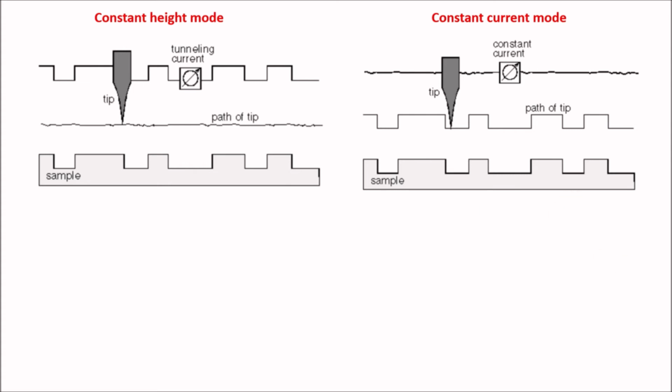The tunneling current corresponds to the electronic density of states at the surface. STMs actually sense the number of filled or unfilled electron states near the Fermi surface within an energy range determined by the bias voltage. Rather than measuring physical topography, it measures a surface of constant tunneling probability.